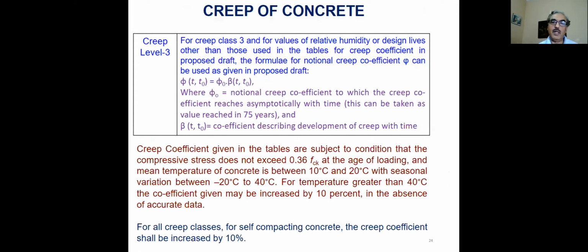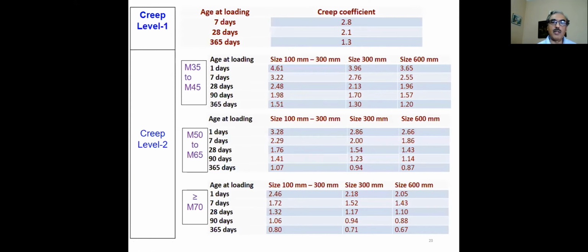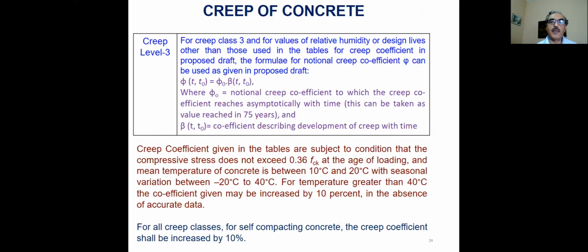In case of higher grades, the creep is less; in case of lower grades, the creep is more. Creep level 3 is when we go beyond 75 years service life, so some notional increase in creep is considered here, and a formula has been given to increase the creep calculated in level 2 to level 3. Then some additional coefficients have been given.